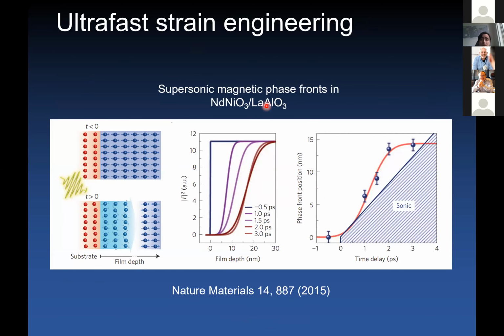One thing that you can do is take your lanthanum aluminate and grow on top an epitaxial layer of neodymium nickelate. You can excite this interesting structural dynamics that I just described in the lanthanum aluminate and observe how the neodymium nickelate film will react. So this neodymium nickelate is an antiferromagnetic insulating system at low temperature. And if you do this type of excitation of the crystal lattice of lanthanum aluminate, you observe that the antiferromagnetic order in the films rapidly melts with the propagation of a wave inside the antiferromagnetic material. So there is a supersonic melting front that propagates in the film, at speeds that are much faster than the speed of sound.